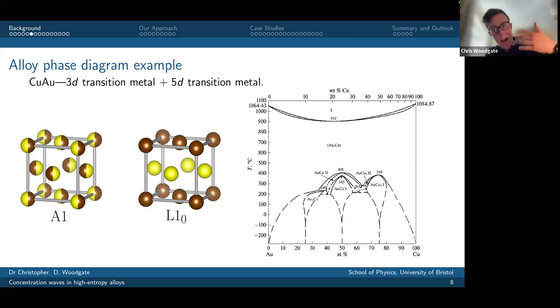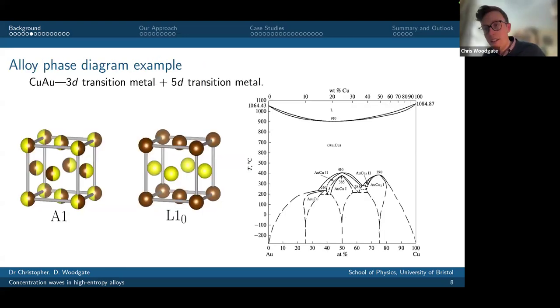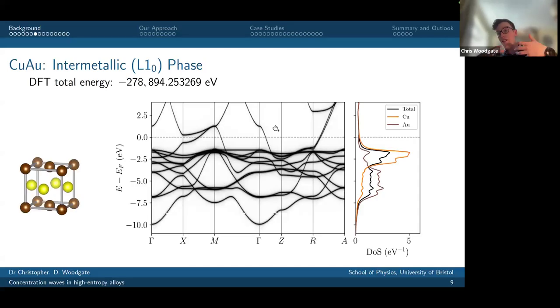Okay, and what I wanted to highlight was how the different phases in these phase diagrams have different properties. And the example I wanted to highlight was residual resistivity, because it's quite a nice fundamental property of a material. If I take the L10 intermetallic phase, the one that's thermodynamically favorable at low temperature, and I do a density functional theory calculation, this is using the KKR method, and here I'm looking at the band structure in the middle, the electronic density of states on the right, and on the left, I'm just illustrating the L10 structure.